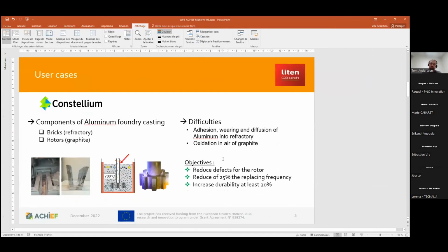Okay. So I was saying that the consortium partner has 2 materials targeted. The refractory bricks on the left side that convey aluminum, and the second material to protect is graphite rotors that are immersed into the aluminum bath. These rotors allow the purification of the aluminum bath with the injection of gas into it. This leads to the impurities going up to the surface.